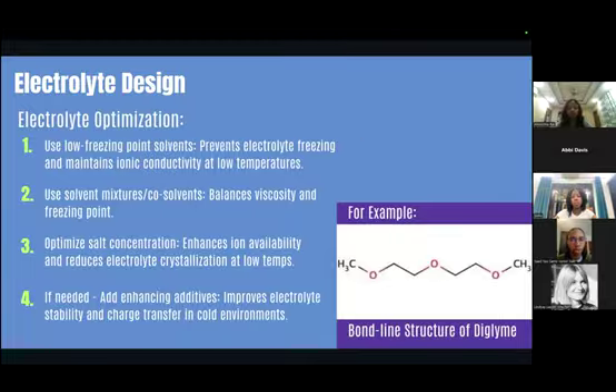And as a solution proposal, we thought of Diglyme because it excels as a low temperature electrolyte for sodium ion batteries. And it has flexible ether chains highlighted by the red part and methyl end groups, which are the two CH3 at the extremities. And they create a molecular disorder that resists freezing, while simultaneously the strategically positioned oxygens form a relay system for sodium ion transport.